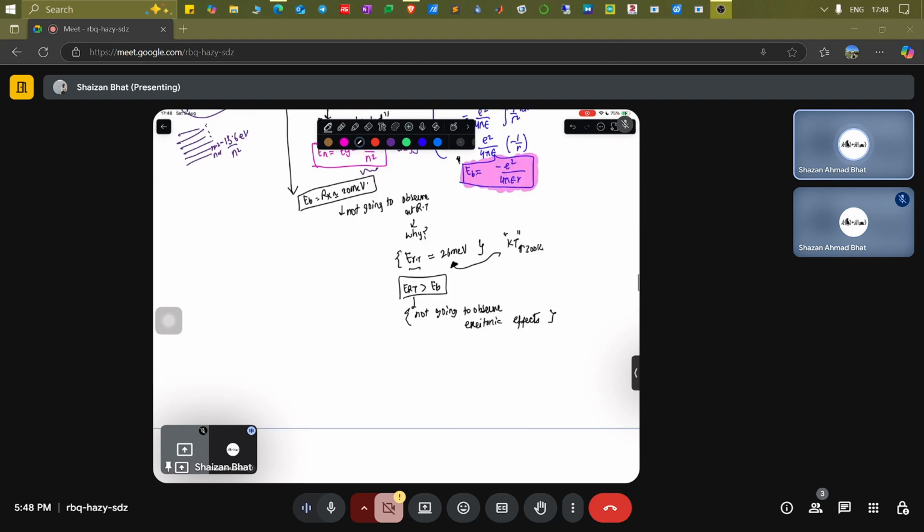That's why you need to go to lower temperature, so that you can have at least the variation of 20 milli electron volt that can be visible. If you go to a temperature, let's say for example 10 Kelvin or 5 Kelvin, then you can see certain variations of this order, 20 milli electron volt or 10 milli electron volts. Okay, so that is the fundamental thing.